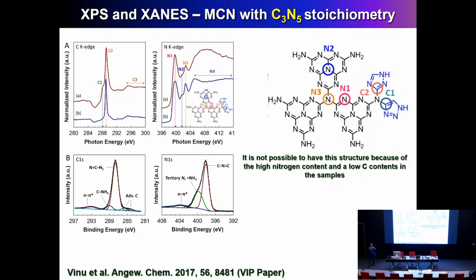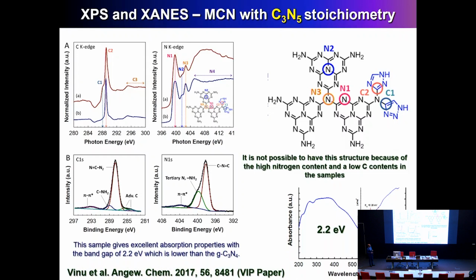So you have a combination of the triazole and triazine into this one, and that reduces the band gap of this material from 2.7 to 2.2 electron volt. So the visible light absorption capacity of this material is much, much better than the C₃N₄. And this is the world's first carbon nitride material with the C₃N₅ stoichiometry with the highly ordered mesoporous structure, right? And we haven't stopped there. Can we make C₃N₆? Can we make C₃N₇ or C₃N₈, right?